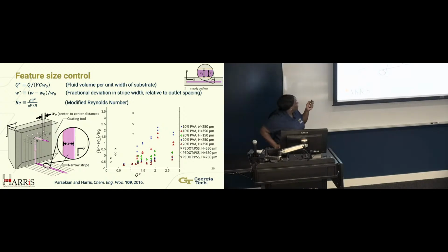So looking at the flow rate, we non-dimensionalized several things so that we could do this study. The flow rate is non-dimensionalized against the flow rate that's pumped in, the velocities, the gaps, and the widths. And then we have the coating width. Again, that's what's actually coated, and this is the tooling opening, so between here and here. And then Reynolds number, which is essentially giving us velocity for this particular work. And what we see is that, ideally, everything is like around here, but it's all over the place, right? These are different materials. So we have different standoff heights, we have different surface tensions and contact angles for all of these materials. And what we know from this is that there is a huge sensitivity. So our deposited lines can be wider, they can be more narrow, or they can be on the dot.